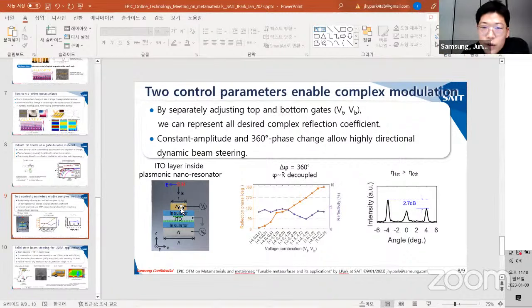Oh, yeah. Very good question. In terms of resolution, we need to think of 2 factors. One is the beam divergence. If your beam is too wide or fat, we might lose some resolution. And the second one is the number of addressable points in the field of view. Actually, it is dependent on the number of independently controllable pixels. So in this work, we came up with 50 independent channels. So the total number of addressable points is equal to the number of channels. So it was 50. But if you can come up with some vertical interconnect access or via, we could make more complicated electrode structures, not just the planar fan out. Then we could increase the number of individual addressable channels to more than 500 or so. So we think we can go beyond several hundreds.